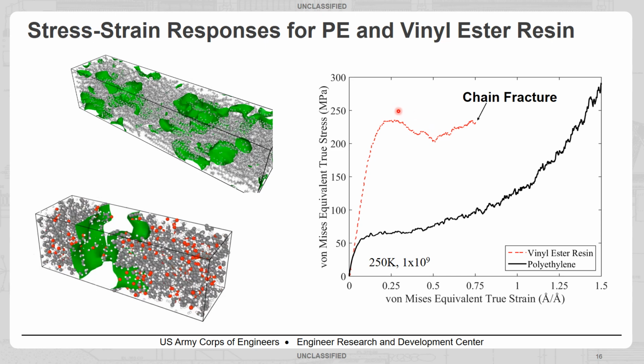Our yield is much higher than the polyethylene, and polyethylene is unique in that it doesn't exhibit any bond breaking during deformation. All the chain deformation is due to loss of entanglements, entanglement pullout. So we don't see a catastrophic failure. We just see very slow, gradual pullout of chains, and in fact, that can last for 500 or 600% strain.